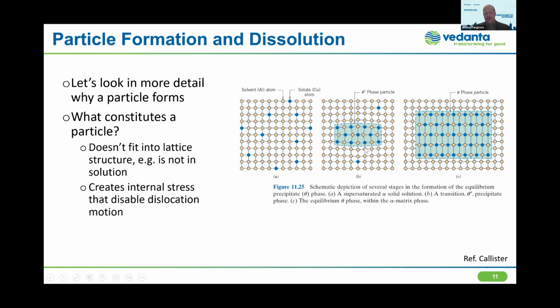They begin to come closer together, which is much easier to happen at higher temperatures. Things can happen more quickly and form a distinct particle that no longer fits in this crystal lattice. So you can see in this schematic, these lines are no longer straight. And that is going to increase the strength, as it will be harder to deform the structure. So when a force is applied, the material will not move the same way it did before, and this particle is providing strength. And then ultimately, you have more distinct particles as they grow larger. Eventually, if they grow large enough, you really don't have that many relative to the small ones, and so you're not adding that much strength.